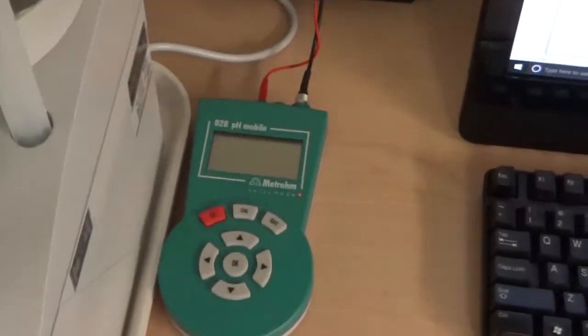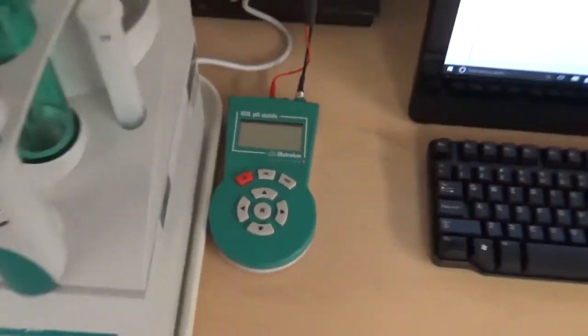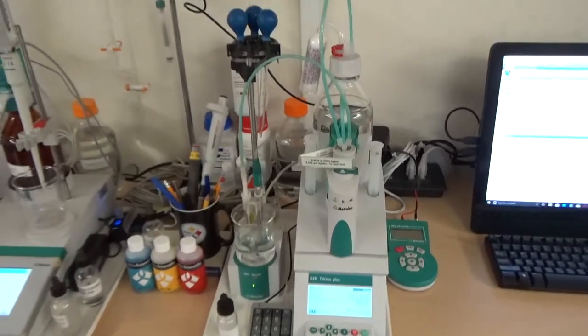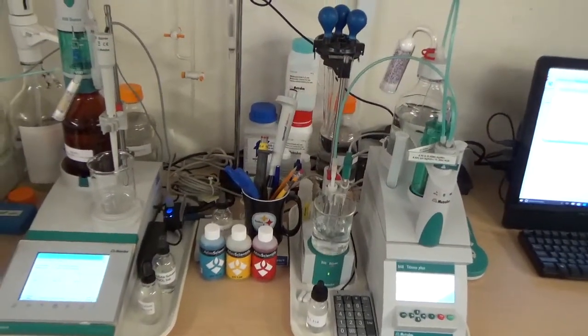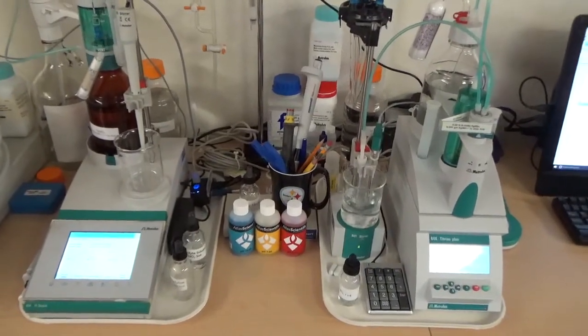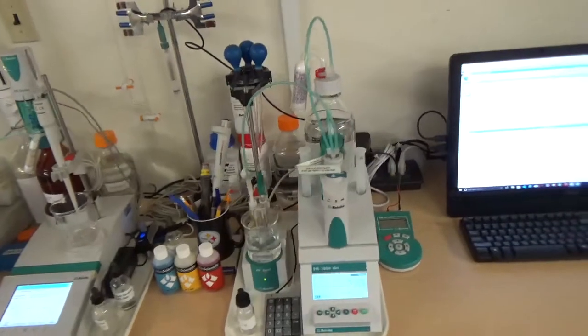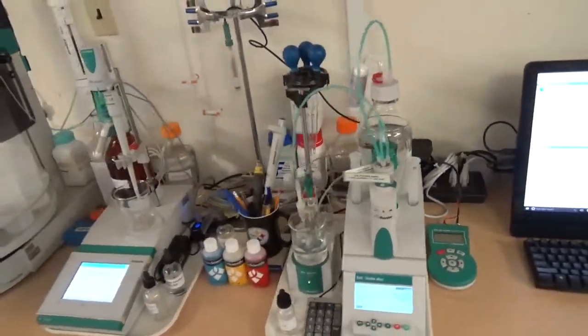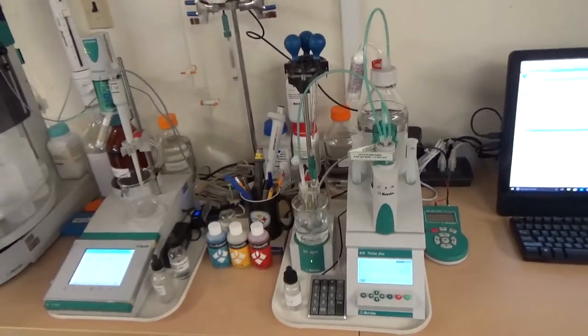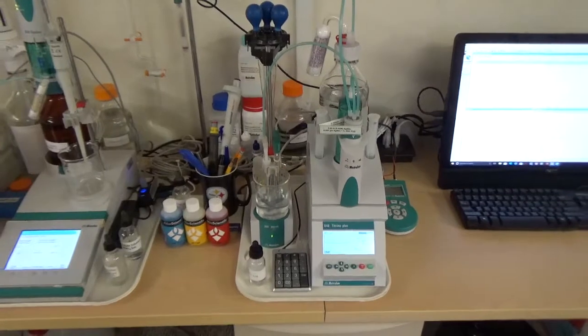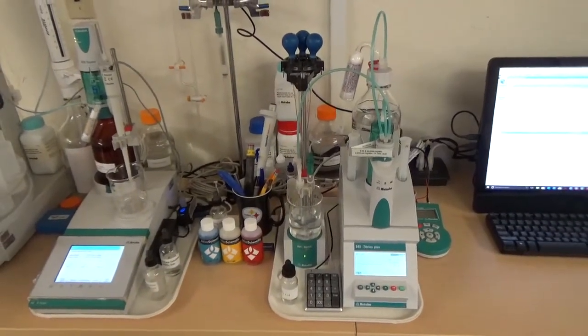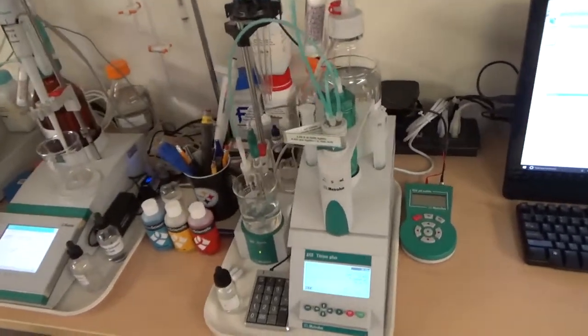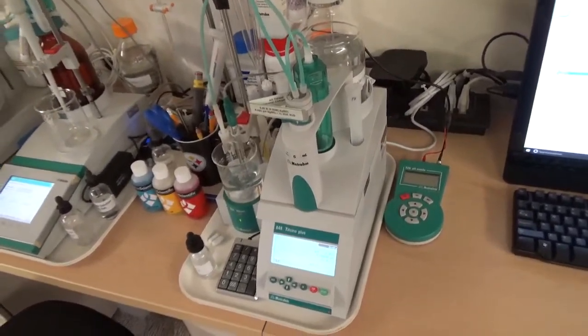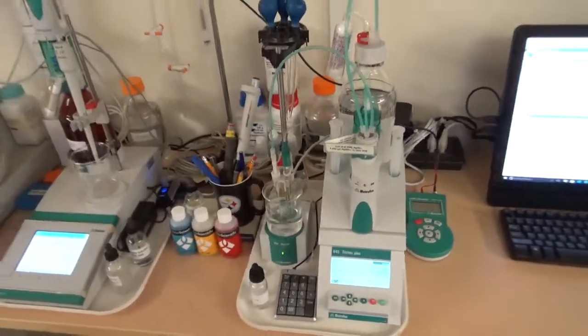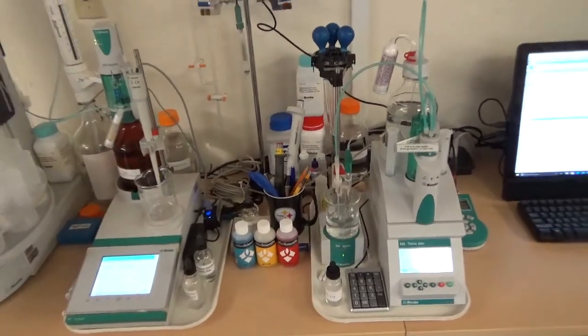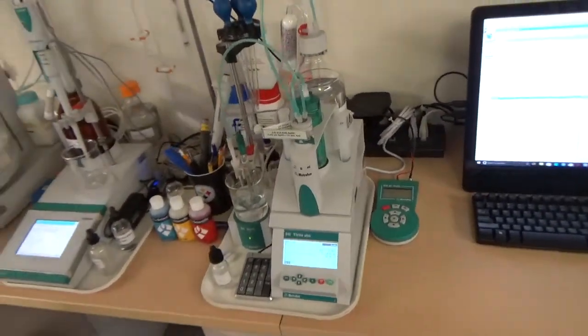This is the mobile pH meter, which we also use to determine the pH of a concrete solution digested in deionized water. For determination of pH, we usually take a pulverized sample of concrete, about 10 grams. We digest it in deionized or distilled water, and then we do the filtration to remove the solid residues. We take the filtrate and then determine the pH of the filtrate. For a normal Portland cement concrete, the pH comes around 12 to 13, highly alkaline, unless the concrete is carbonated, then the pH goes down to 9, 10, in that range.